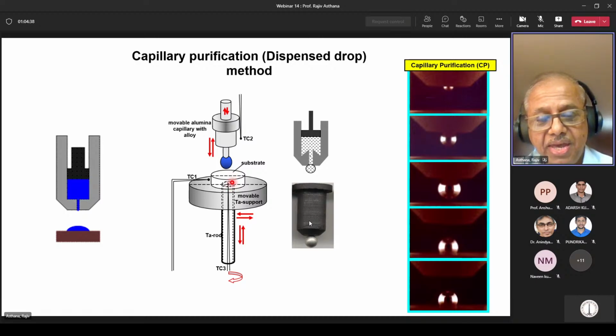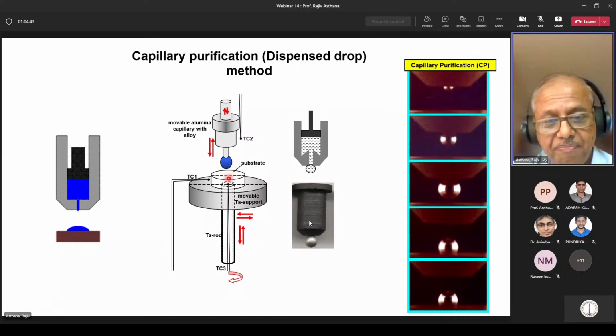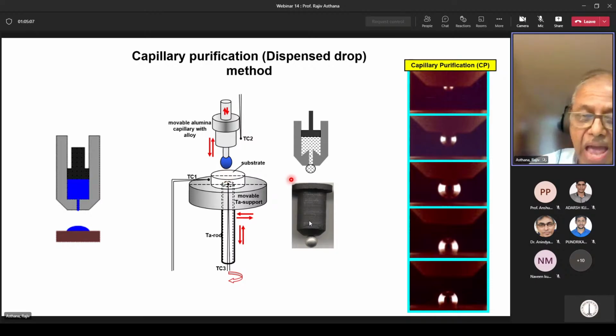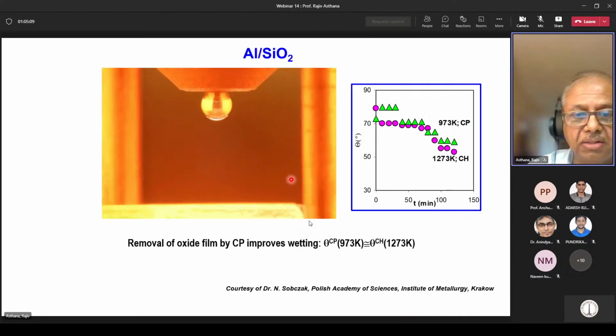Two, that you are not heating the two things together until melting, so you can actually see the reaction between liquid and solid, not the reaction that takes place during heating of the solids in contact. And the third point is the most critical one. That is, when you squeeze the liquid out of the capillary like this, you are actually eroding or destroying the surface oxide film. So this gives you a more accurate measurement of contact angle.